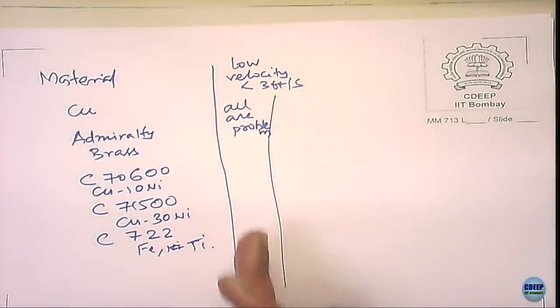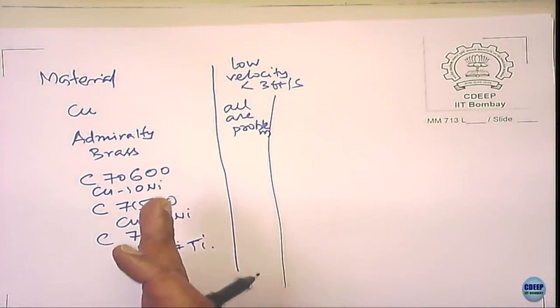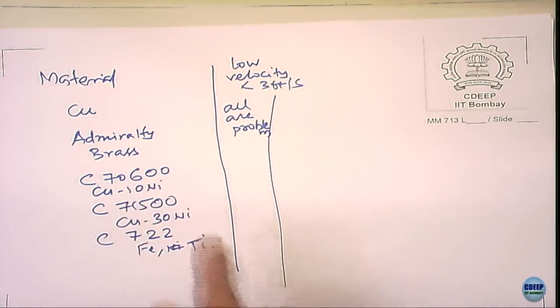Low velocity is also a problem. See, most of the process fluids might have some kind of particles, you know, second particles, dispersed particles. Sometimes in heat exchangers, if you see water, maybe some foulant. When the velocity is very low, then what happens? They start depositing on the surfaces. It's not an erosion corrosion problem, it is another kind of problem that you're going to get, okay. And so you normally have problems in these cases.